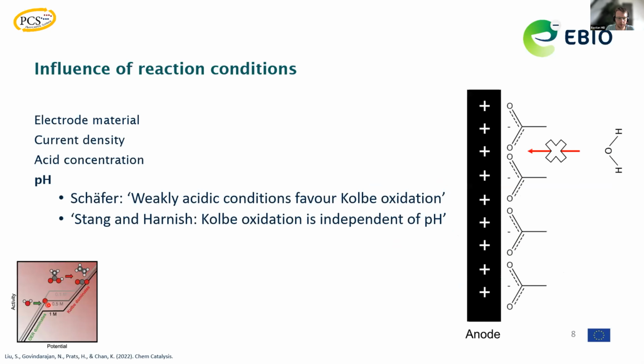And that's what we're going to show in a moment. So what is happening in this plateau region? It was advertised that at the anode material, the negatively charged acetate ions are adsorbing at a certain potential, and thereby inhibiting the oxygen evolution and favoring the oxidation of the acetate molecule, thereby even favoring the formation of Kolbe products or non-Kolbe products. And of course, you can imagine that if you have a high current density, so a high abundance of these radical species at the surface, they tend to recombine to form the Kolbe product, while at rather low current densities, you might envision that you're actually obtaining the favorable Hofer-Moest product in the end.